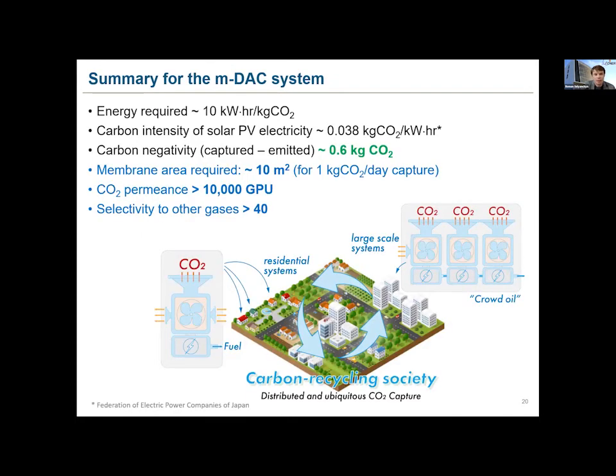And with this, I would like to summarize my talk and to show that we have designed this MDAC system, membrane-based direct air capture system, and energy required is around 10 kilowatt per hour per kilogram of CO2. And considering that the energy which will power this system will come from renewable sources, for example, solar PV electricity, we can say that this system can provide a carbon negative process, and at least 0.6 kilograms of CO2 can be captured. And the membrane areas are in practical range, around 10 square meters per whole 3-stage system.